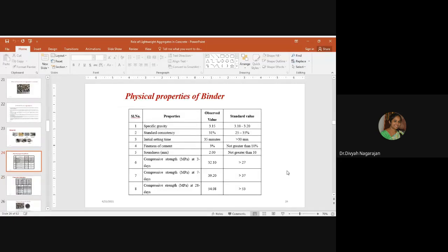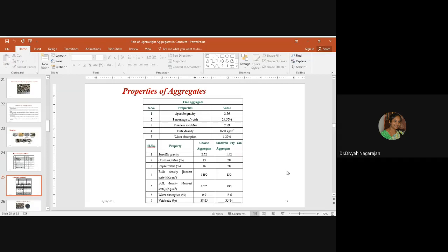Physical properties of the binder. OPC cement, Ultratech cement of grade 53, was used in this investigation with a specific gravity of 3.15. The 3 days, 7 days, and 28 days compressive strength tests were carried out systematically, and the 53 grade was obtained. Physical properties of the aggregates. The fine aggregate, as I said earlier, was naturally available river sand. The specific gravity of the aggregate was 2.56, and water absorption was around 1.2%, which is usual and normal. The size of the aggregate was 4.75 mm down passing.